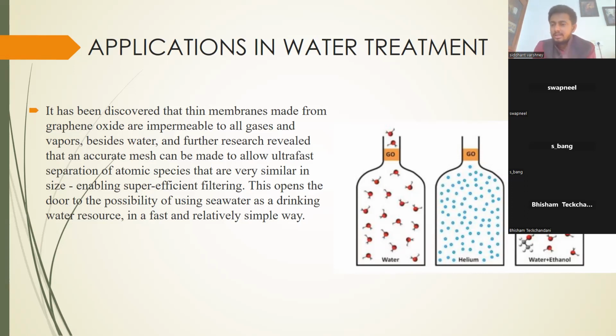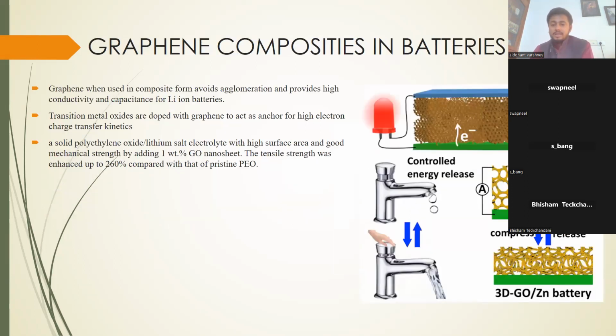For both these kinds of membranes, graphene is a very good candidate for water desalination, even for selective ion capture, for ion exchange reagents. It is being used in ion exchange reagents because the surface activity and the surface area of graphene is very big. I would say that 1 gram of graphene has a surface area of 2 football fields. It is that big. So the surface area plays a very big role in desalination or ion capture. You won't have to change the membrane many times, and it is also selectively permeable to heavy ions. Being selectively permeable, it can be engineered for what kind of ions you want through it and what kind of ions you want trapped. Especially with heavy metal ions, it is very efficient.